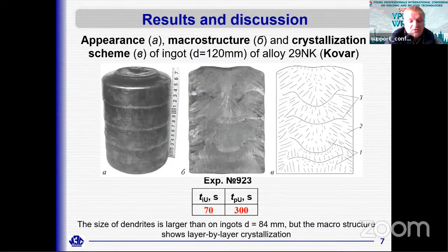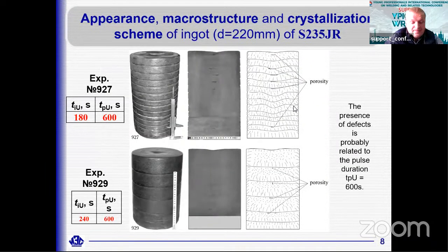We also have ingots of diameter 120 millimeters of alloy Kovar. The size of dendrites is larger than in the ingot of diameter 84 millimeters, but the macrostructure shows layer by layer crystallization. In addition, experiments were performed on ingots of diameter 220 millimeters of this steel. The use of ESR affects crystallization, but the effects we found are on the macrostructure of ingots.